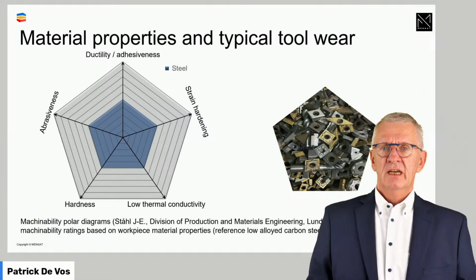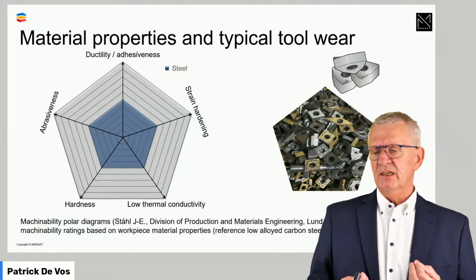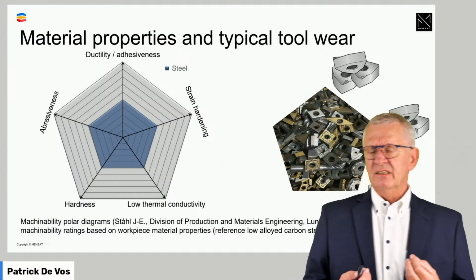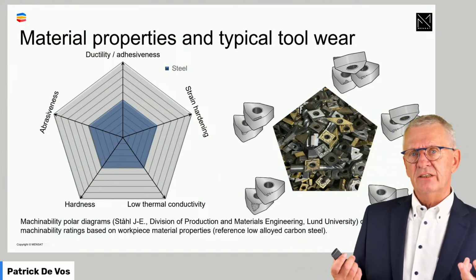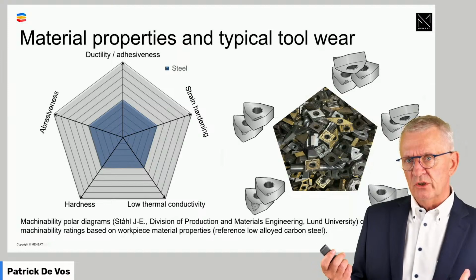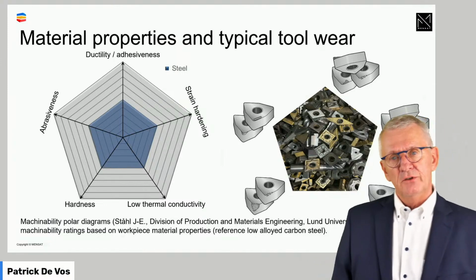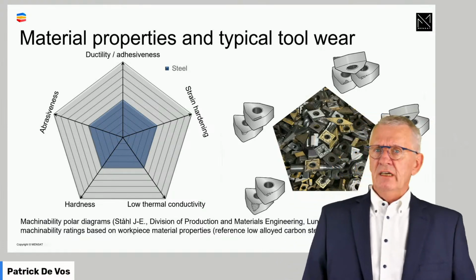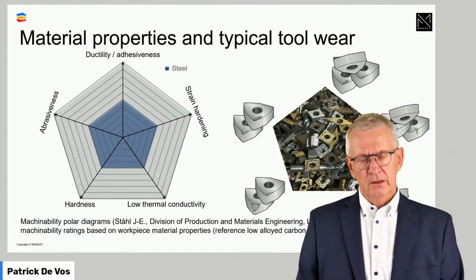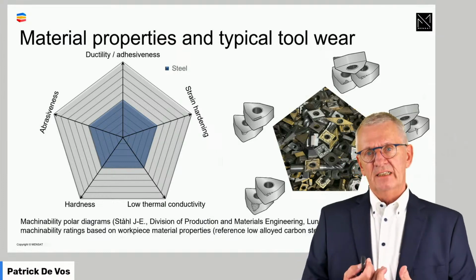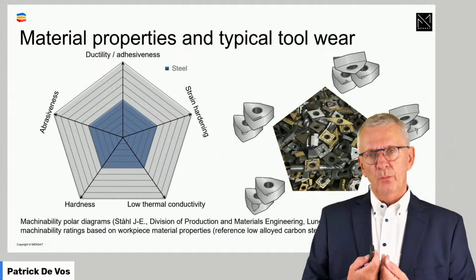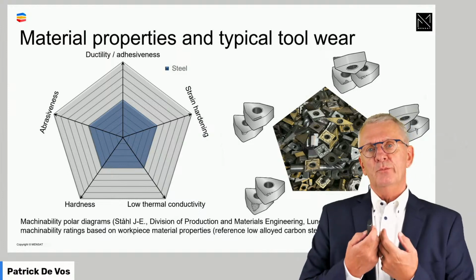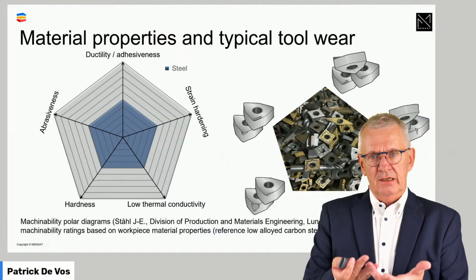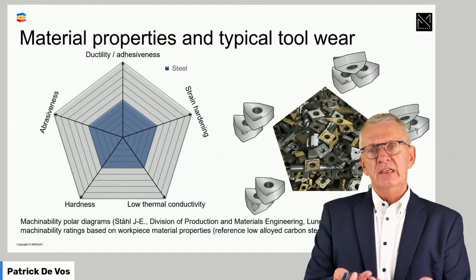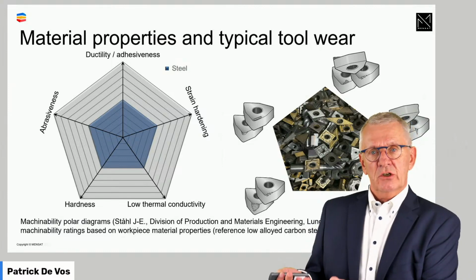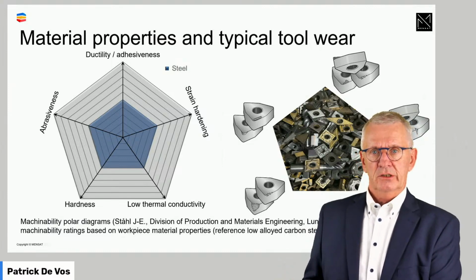into consideration. And the interesting thing about this model is that the old saying that flank and crater wear is the only acceptable wear during a machining process, which is very correct if you machine steel, but does not really work if you have to machine another material, we can improve that. We can say it's one of these 5 properties, and to which extent the property is present in the material, that if you machine the material, you will see a certain typical wear pattern on a cutting edge.